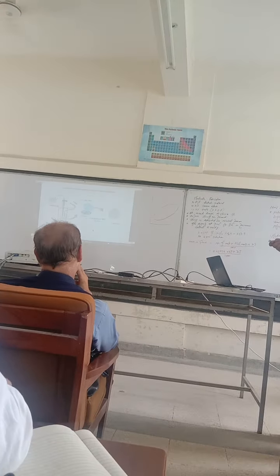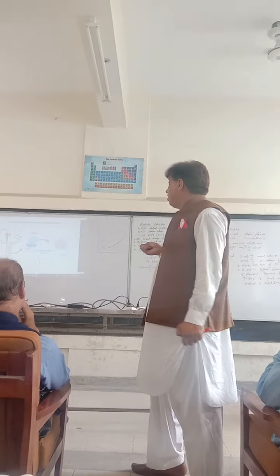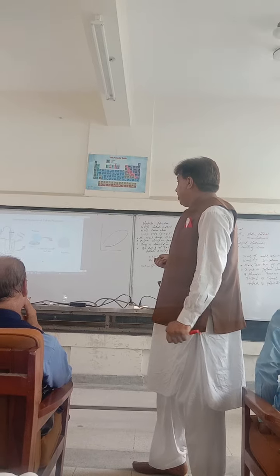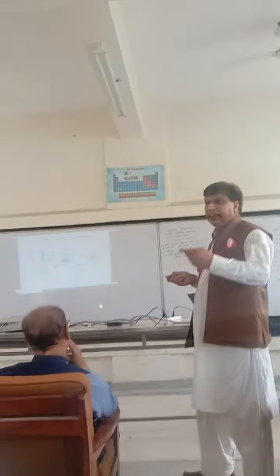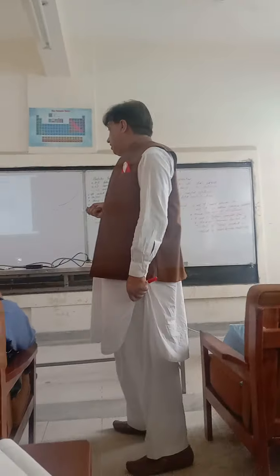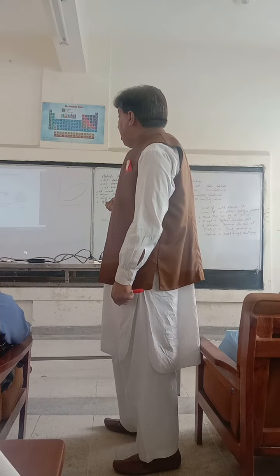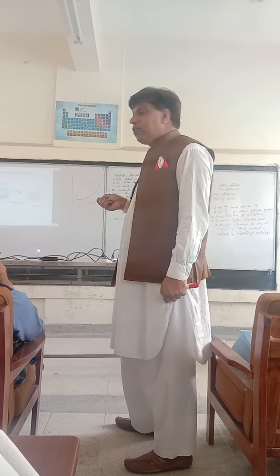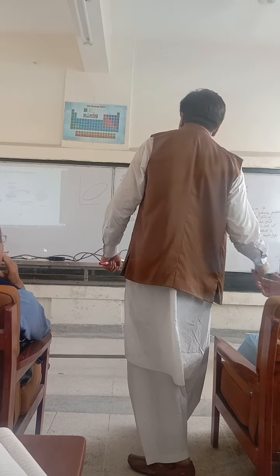So first of all, we synthesize our precursor material, the host material, cobalt phosphate. How do we synthesize this cobalt phosphate in the lab? First of all, we take a 0.05 molar solution of cobalt chloride in deionized water, and then place it in a beaker under the probe sonicator.